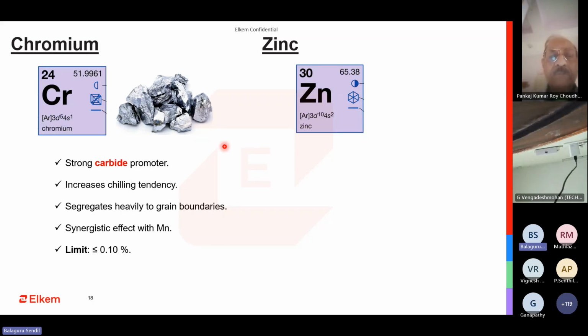It can combine with manganese and then segregate to the grain boundaries, and it doesn't allow the metal to solidify. Your solidification temperature will come down. Because of that, you might end up with some micro shrinkages and micro porosities. So that is a real world problem of having high chromium. But a bit of chromium, 0.1 to 0.15% in gray iron, can cause a bit of matrix refinement, which is good if you're trying to have a good surface finish post machining. So that is the advantage, but mostly in ductile iron it has a very strong disadvantage.